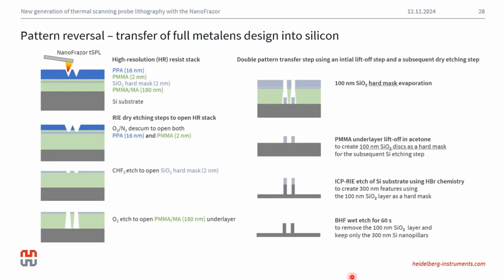The way we do so is going back to our high-resolution transfer methods, again using a high-resolution resist stack. In the first step, we launched the patterning on top of PPA, and then using a series of dry etching RIE steps, we transfer these patterns down to the silicon substrate. In this case, instead of depositing and lifting off a metal layer, we deposit 100 nanometers of silicon dioxide and lift it off. And it's these silicon dioxide disks that will act as a hard mask for the subsequent etching into silicon. In this particular example, we also use a special ICP RIE to perform the etching into silicon. This uses HBr chemistry and allows us to get very good straight sidewalls and smooth sidewalls. I'll show SEM pictures of the resulting features in the next slides as well.